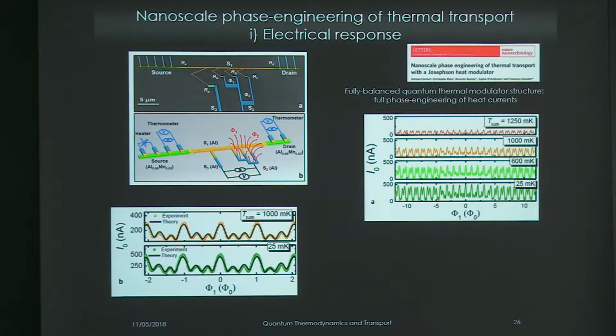The idea was to show that in an interferometer that is fully balanced by construction, it's possible at the end to have the full suppression of the supercurrent. So we realized a sort of multi-loop, in this case a double loop system. The system was similar to the first experiment, but thanks to this very different ratio between the two areas of the interferometer, you have very complicated beating patterns of the Josephson critical current. Okay, so thanks to this difference in the area.